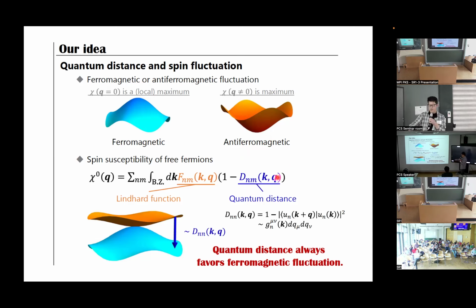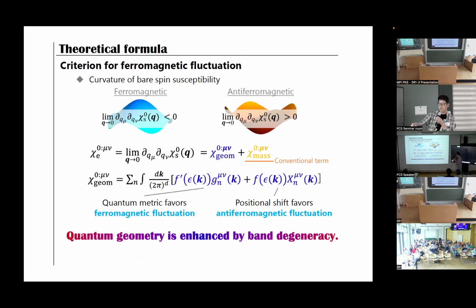Okay. So in order to formulate these ideas, we calculated the curvature of magnetic susceptibility in free fermion systems, and it is obtained like this. We have two terms. One is coming from the conventional ferromagnetic theories, and this term is mainly determined by the nesting properties of the Fermi surfaces. But in addition to these conventional terms, we obtained the quantum geometric correction to the curvature of spin susceptibility. And this term is further divided into two terms like this.